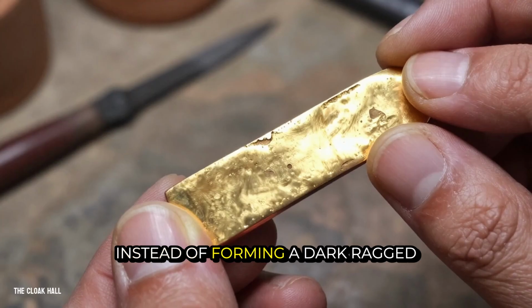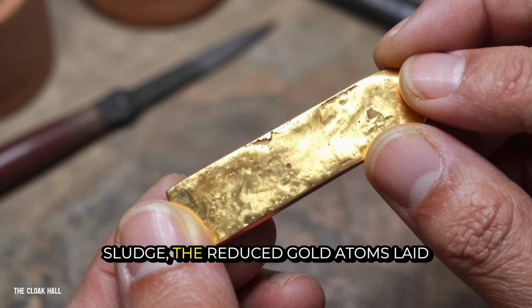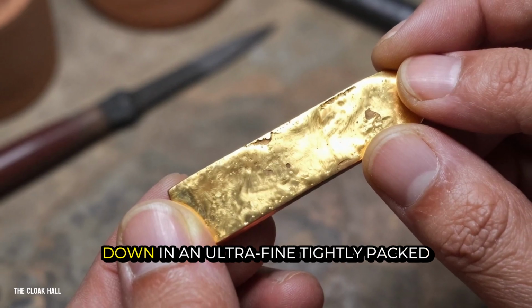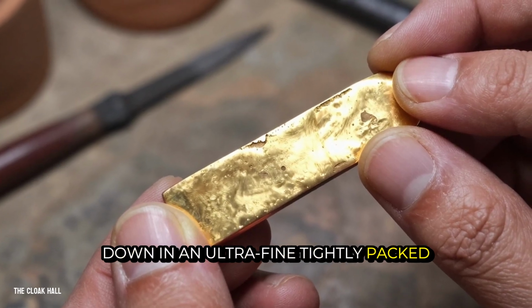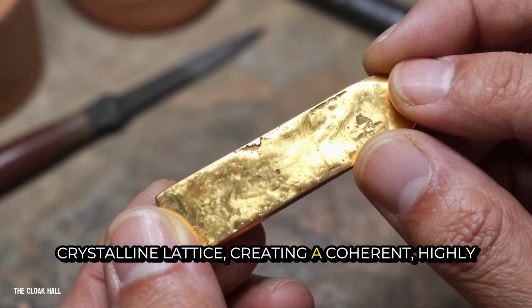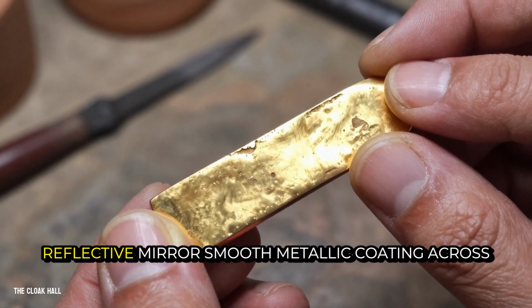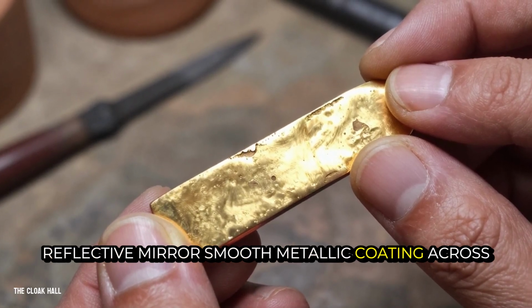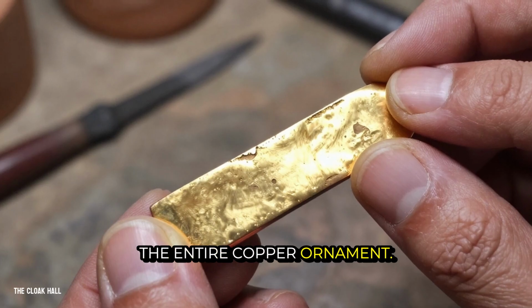Instead of forming a dark, ragged sludge, the reduced gold atoms laid down in an ultra-fine, tightly packed crystalline lattice, creating a coherent, highly reflective, mirror-smooth metallic coating across the entire copper ornament.